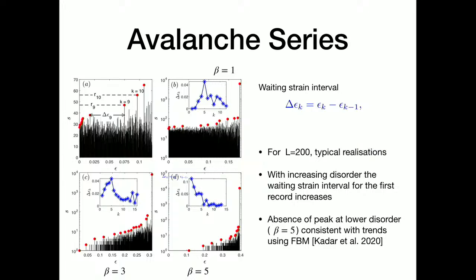You have the highest strain, this is the highest strain, that is for the first record, but subsequent records require less and less deformation, and you are approaching failure. So there is a sort of acceleration. When you look at the intermediate disorder, the lowest disorder, beta equal to 1, has only 2 records, very few or 1 record. So we are not doing any statistics of that.